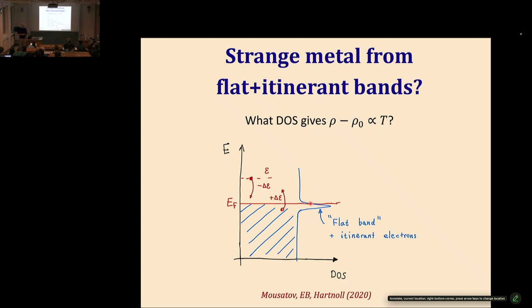This is not very easy to obtain. Unlike just having a 2D Van Hove singularity at the Fermi level, which in a 2D system, whenever you tune some parameter, you'll inevitably get. Here you have to have this perfectly flat band, which is not a very natural or easy thing to get. It needs to be flat on the scale of kT, which means that if you go to lower temperatures than the bandwidth of this flat band, the linear in temperature behavior would be modified. And flat bands, just like Van Hove singularities, but in a more extreme way, tend to become unstable. The system doesn't like to have a large degeneracy. Quantum mechanics doesn't like a large degeneracy close to the Fermi level, so the interactions would tend to destabilize the system at low energies.